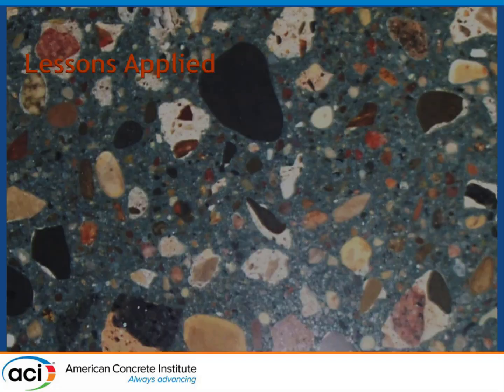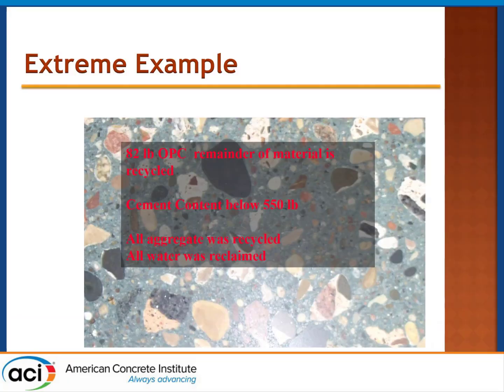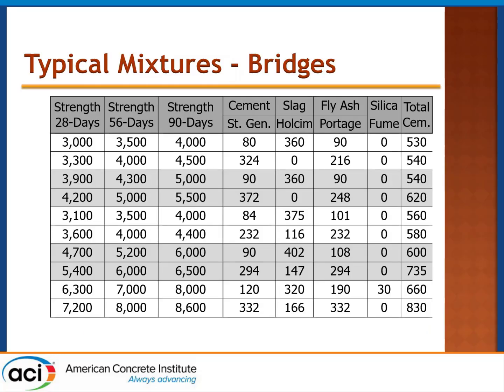The concrete looks really nice. You can see the very green-blue paste that's full of slag and the recycled aggregate paste. Some of those recycled aggregates completely stripped of paste fraction. Some of them are all paste fraction. 82 pounds of ordinary Portland cement. Everything else was recycled. All the water was reclaimed. And we were surprised. We've been doing this for mass concrete. We were surprised at the durability. And this led to us designing a bunch of concrete for a bunch of high-performance bridges that are throughout Minnesota.